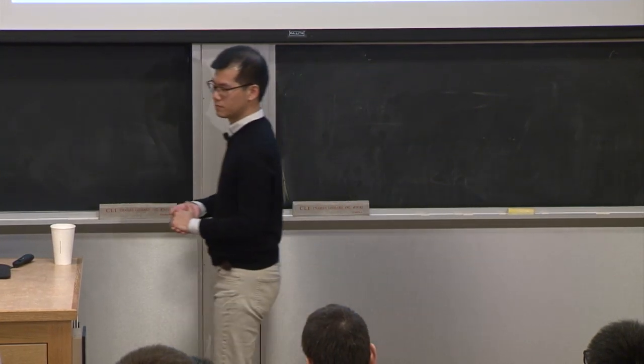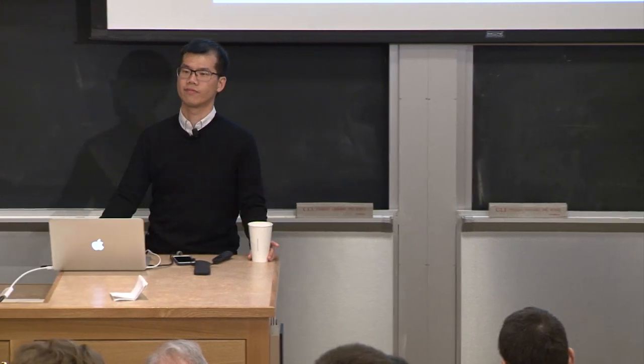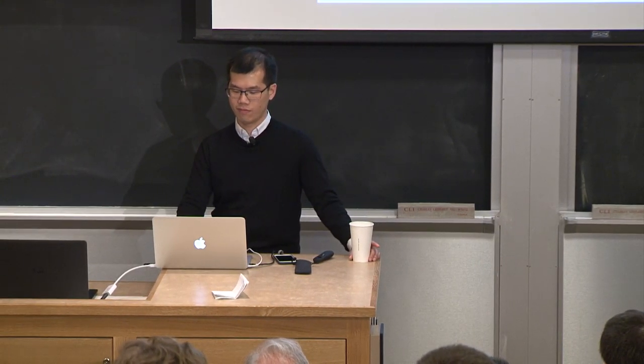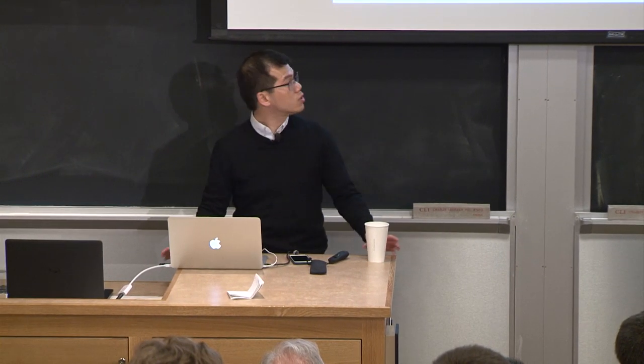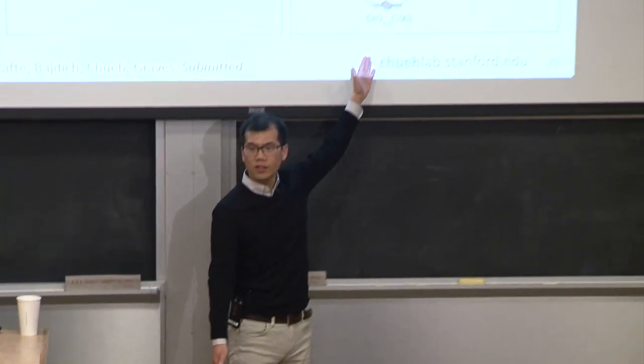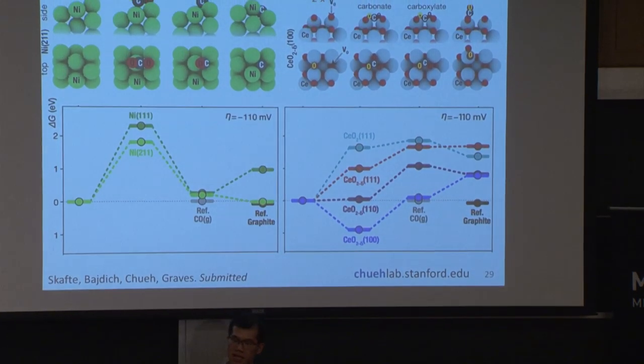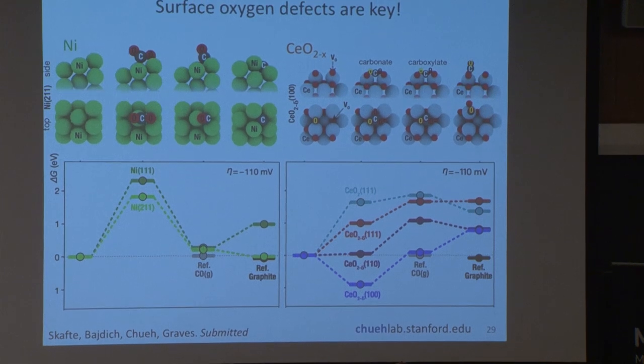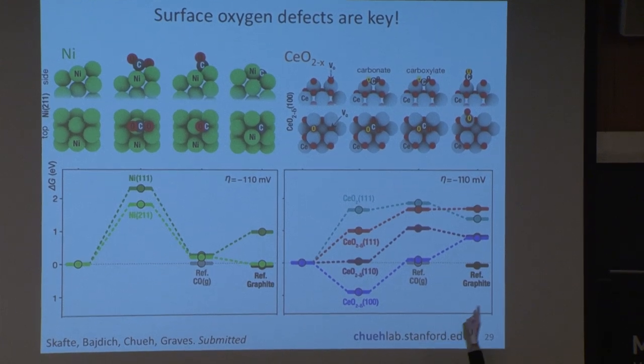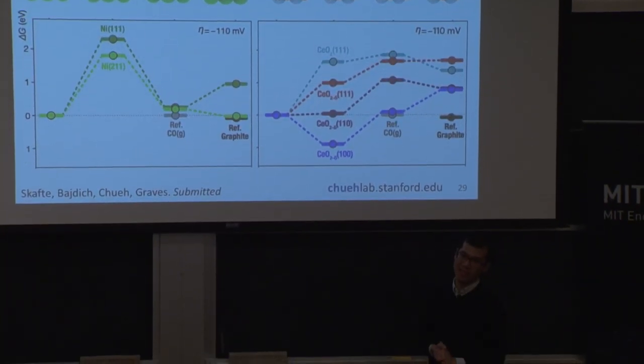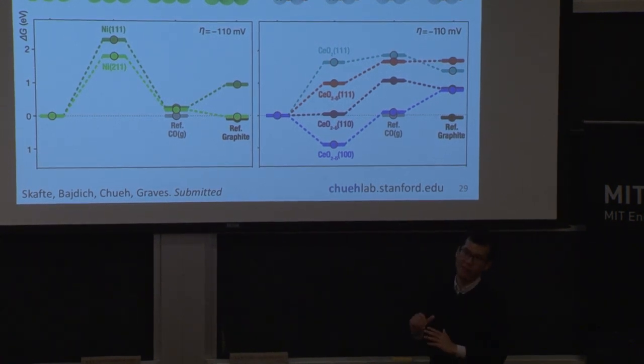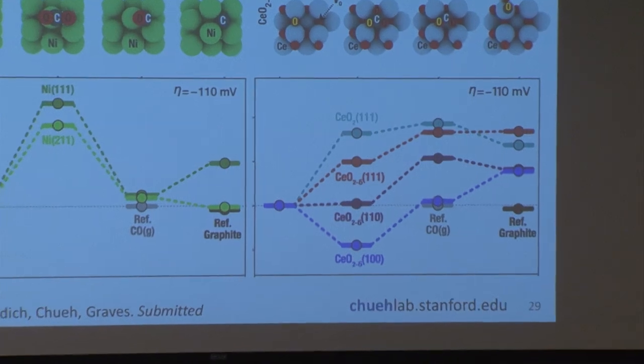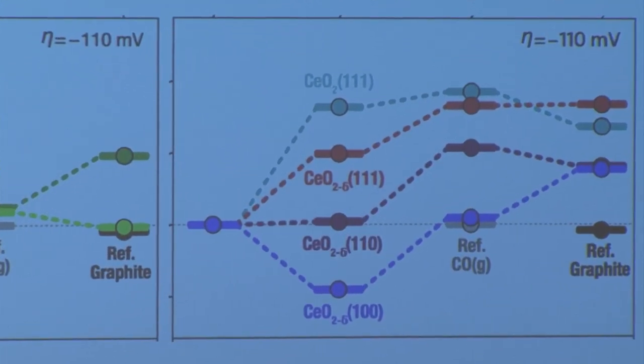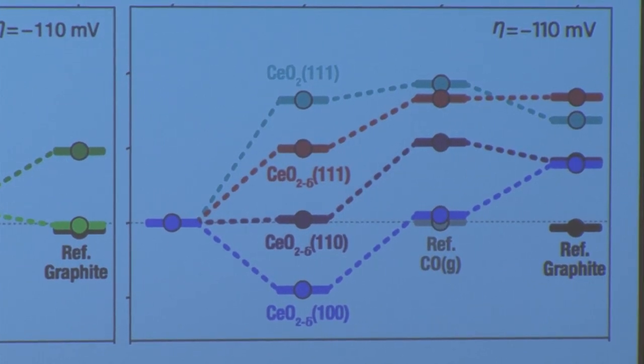So it's the relative stabilization of the carbonate relative to the carbon monoxide, right? Yes. Okay. So what you want is this well to be deep, but not too deep. Because if it's too deep, it can't come off as CO. But you also want it to be deep relative to the carbon. And that's the key. And then there's a kinetic aspect to it. The deeper it is, the more coverage you will have. And the more carbonate you have, the more oxygen you have around the surface to remove any carbon that you might deposit